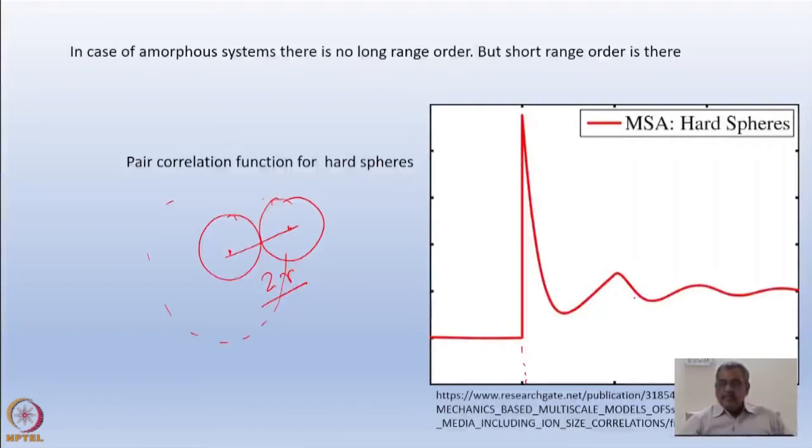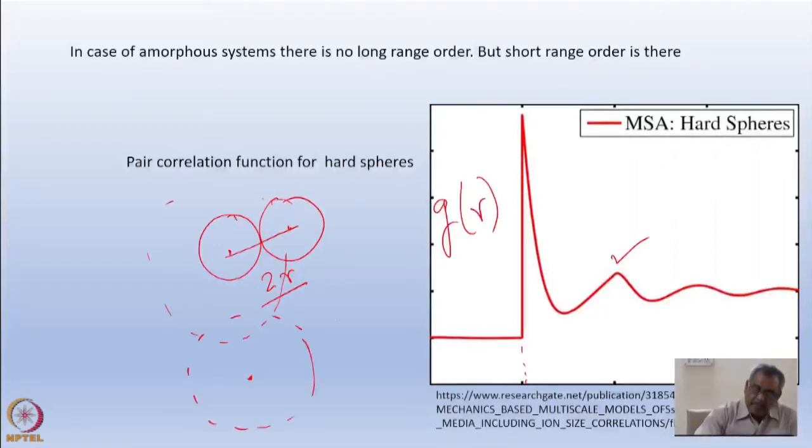You can see what happens actually: the second shell around the central atom. The central atom can be anywhere, and it is an average over various ensembles of the hard spheres. So this average shows the nearest neighbours and a very sharp first peak in the g of r. This is g of r versus r. Then there is a second peak. So if I have a center here, the first one is pretty well defined, but the second one is diffuse,